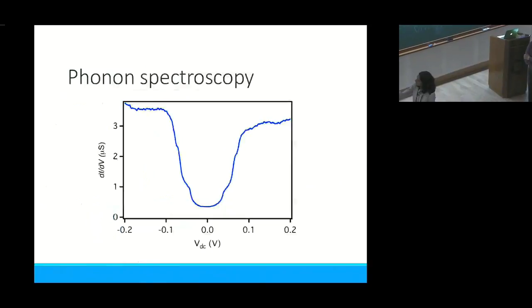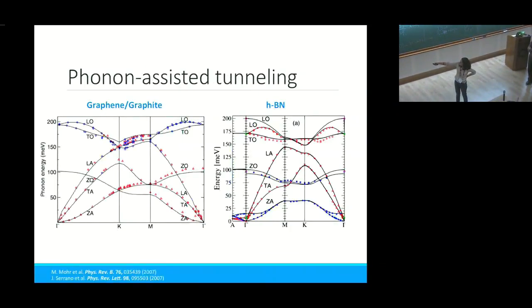Looking at this dispersion, we have signatures of this one, then over here, and some phonons over here. But here it's kind of crowded, so we have a peak that's skewed out, not very sharp. But we see four particular phonons contributing. Question about directions: We do have Z modes which couple. Those are the ones which are very strong. There have been theoretical works predicting that Z modes couple better, and we see that the main bigger two peaks are coming from the Z modes.